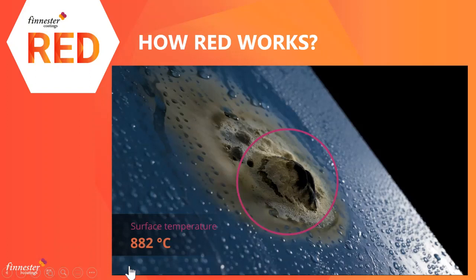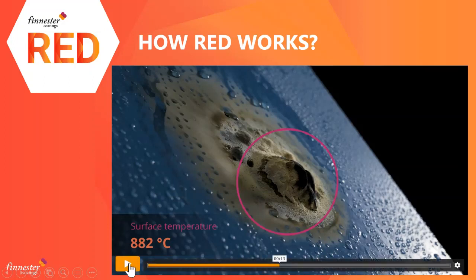material. And what happens also in a controlled manner is that the heat is transferred from the ceramic material to the other side of the coating, and that will hit the pure red layer, and that will start to expand, and that's why the bubble is formed. But instead of expanding too much, the ceramic shield is formed on the top of the intumescent layer, and that keeps the intumescent protected and prevents it from falling on the floor. So in that controlled manner, we can introduce a new way of protecting the composites without changing the composite.